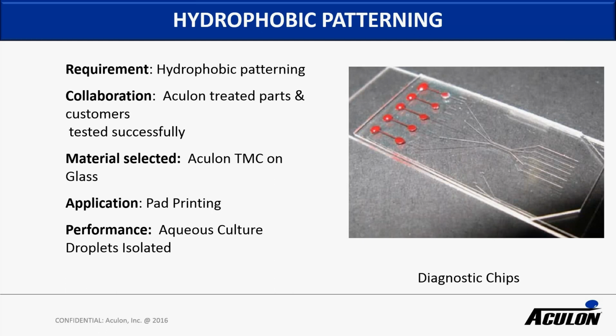Another interesting area for medical devices is diagnostic chips, where there's been a need for isolating droplets. We had a customer come to us that needed to grow cells in certain areas on a chip, and so we developed a pad printable TMC formulation that could be applied and pattern the surface so that the droplets, once dispensed, would stay in the locations where they were dispensed.